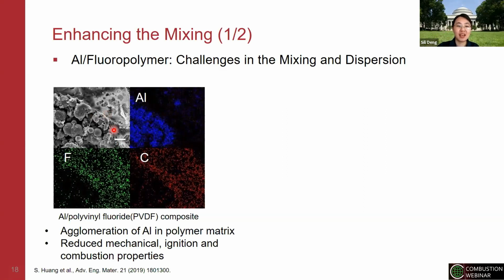As you can see from the SEM images and the EDS elemental mapping, all the aluminum is clustered here, and the fluoropolymers are outside. So although globally they're mixed, locally they're still separated, which would inhibit the ignition and the combustion performance. And also, because of the separation, it will reduce the mechanical strength of the composite as well.